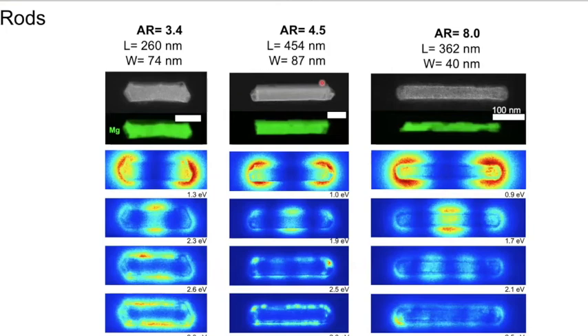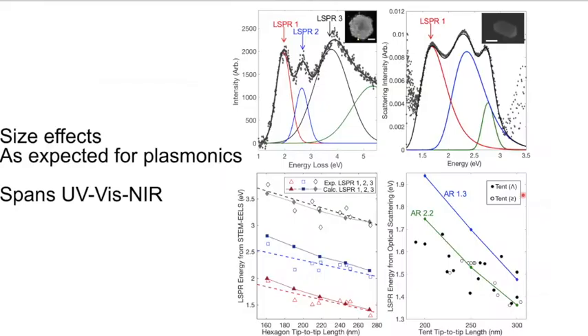And as the particle shape elongates more and more, what you get is exactly what you would expect for rods, where all of the transverse components are now essentially suppressed. You're only getting longitudinal components, and really quite high order of these longitudinal components. So here's an example of a rod on the right with an aspect ratio of 8. We can see the L equals 1, L equals 2, L equals 3, L equals 4 modes, and so on. It's kind of reassuring to see that, because this is what people have seen for decades in gold and silver. So magnesium might be a new material, but fundamentally it has the same behavior as any plasmonic structure.